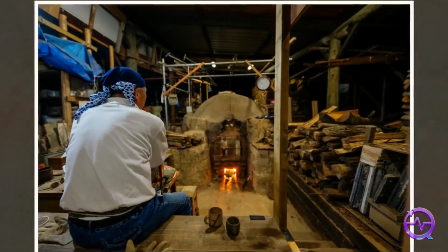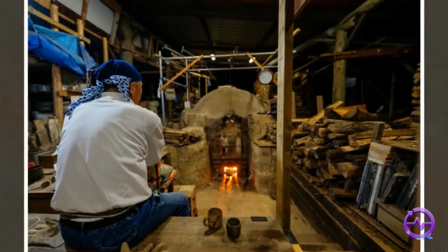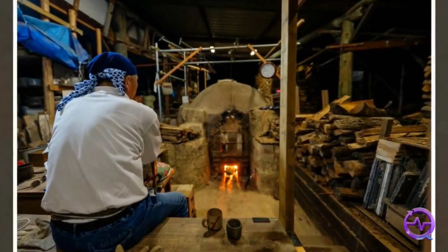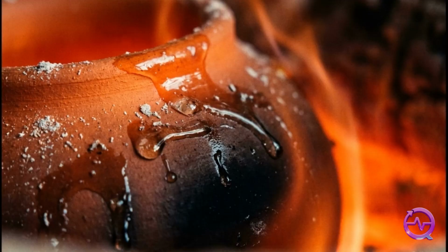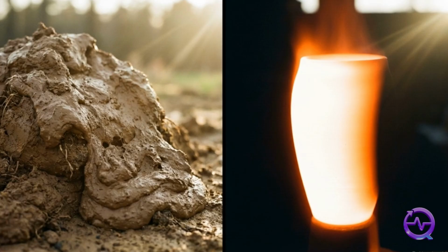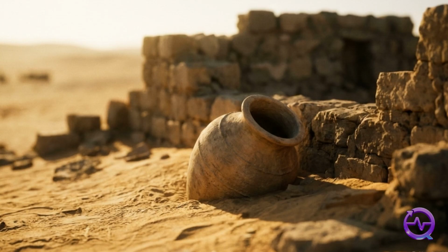In Japan, the Anagama kiln utilized a tunnel-like design, where the draft carried wood ash throughout the chamber. At peak temperatures, this ash melted directly onto the clay, creating a natural glass-like glaze. Capturing this level of heat was the final technological leap required to transform fragile, water-soluble mud into a durable substance that can survive for thousands of years.